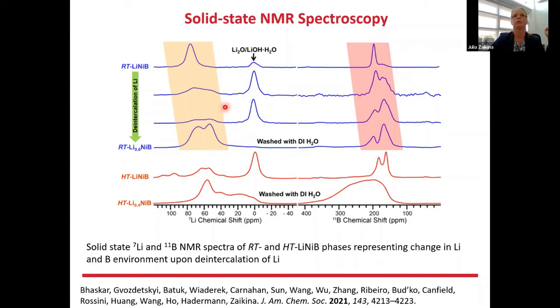And we do also see the increase in the peak corresponding to the lithium oxide. So when material is exposed to air, lithium is going out and forms lithium oxide. And then once this sample is washed with water, we only see the deintercalated material, and particularly the lithium in this deintercalated material. And there is also a change in the boron environment. And again, similar behavior is observed for the high temperature polymorph.